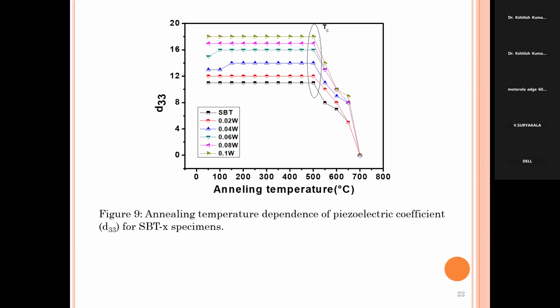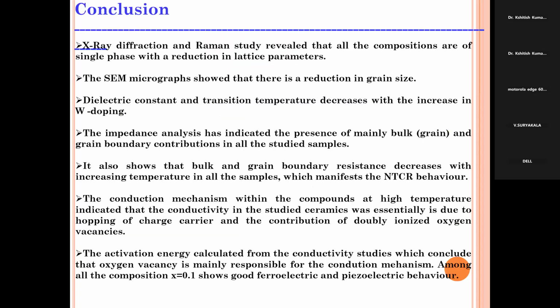So I have already told that recently we have published a paper for the high temperature piezoelectric sensor application for aerospace engineering, and we proved that this material can be used for aerospace engineering, and these are the conclusions. The grain size decreases from the SEM study, and the dielectric constant gradually decreases. Impedance, grain resistance, grain boundary resistance, we found out, and we have correlated with the conductivity, and also we have correlated the conductance with the resistance values. And finally we find out the ferroelectric constant, the dielectric value, and the piezoelectric value in the material up to a high temperature.